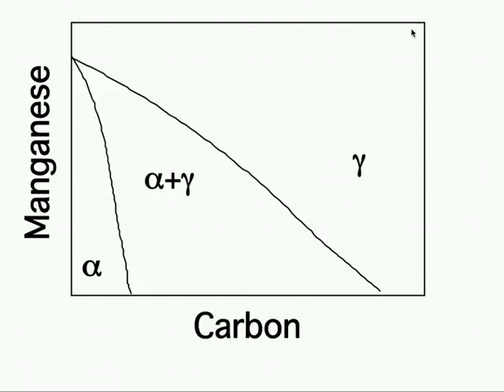Now it follows that the tie lines on this new phase diagram, which is not an equilibrium diagram, but we call it a para-equilibrium phase diagram because the manganese is not partitioning, will be almost horizontal because the manganese to iron ratio in the ferrite will be the same as the manganese to iron ratio in austenite. It's not exactly horizontal because the carbon concentrations in the ferrite and austenite are different. But the tie lines are almost horizontal throughout this phase diagram.